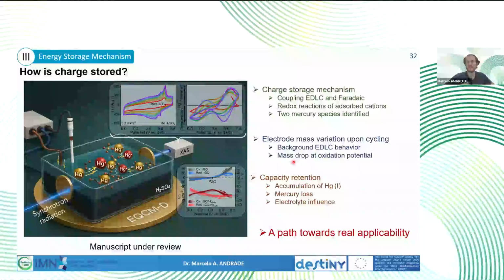So that's to conclude on this topic. We could actually see the coupling between EDLC and Faradaic processes on XAS. And we could see mercury was a mobile species during cycling, both by XAS and EQCM. Mercury 1+ was accumulating, and there was a total mercury loss throughout cycling. And for sure, the electrolyte really influences the performance of these types of devices, right?